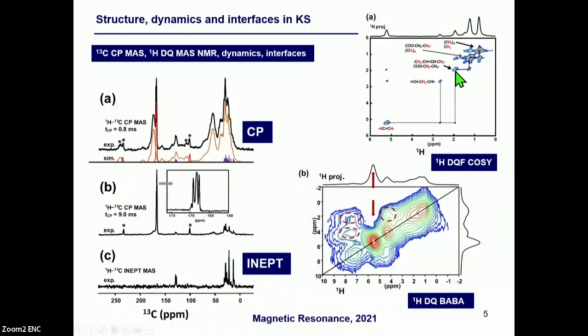If you want to look at the interfaces between the organic and inorganic components, then you can switch to traditional dipolar recoupled experiments, proton-proton double quantum experiments, such as back-to-back, which is very robust. And in this case, and in favorable cases, you can extract correlations corresponding to the interfaces.